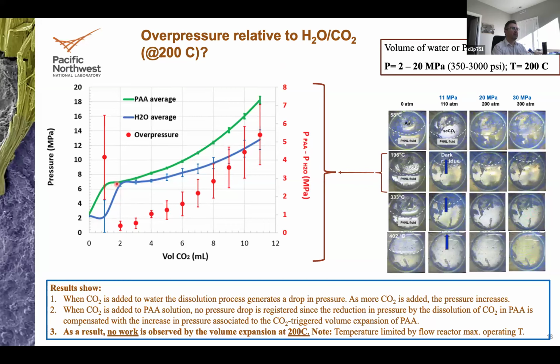Then we open that valve and we continuously add more CO2. What we see is an increase in pressure, obviously, in the water solution as well as in the PAA solution. Yes, the volume expansion leads to higher changes in pressure for the same volume of CO2 than in the case of water. So the volume expansion does increase the pressure higher at any volume of CO2 than in the absence of the polymer. But what we believe is that at this temperature, 200 Celsius, there is no work associated to the volume expansion. So at 200 Celsius, we cannot say that the fractures were generated at lower pressure because there is a volume expansion and a localized pressure in that wellbore, that small wellbore that we showed previously.